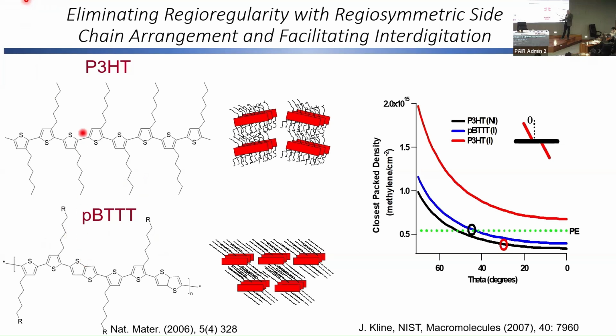We've just basically taken the poly-3-hexylthiophene, and we've introduced a thienothiophene, an unsubstituted thienothiophene group, to add a little bit of distance between these alkyl chains. You can see here these alkyl chains now are much further spaced apart. And very simply, that means now that vertically neighboring chains can come down and allow this interdigitation. And this is a process of self-assembly that encourages now a very nice degree of three-dimensional registration. So each layer is now registered to the layer above it, and we've got a large three-dimensional order.